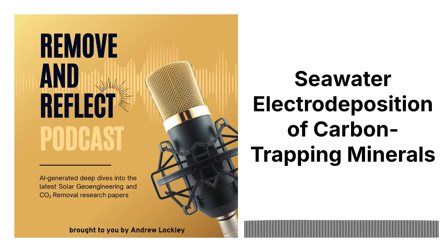And this carbonation process has other advantages beyond just storing more CO2, doesn't it? It does. What else does it do? Well, they found that this carbonation process also altered the internal structure of the aggregates, generally making them less porous and significantly increasing their overall strength. Okay, so it makes them more durable. Exactly. For example, the compressive strength, which is a measure of how much squeezing force a material can withstand, jumped from around 1.4 megapascals to over 6 megapascals after carbonation. Wow. So more than 4 times stronger. Yeah, it's a significant improvement.